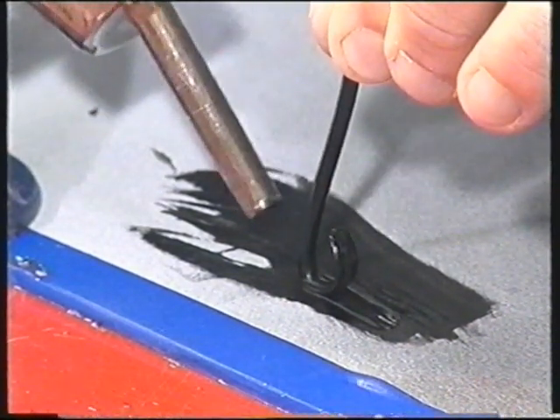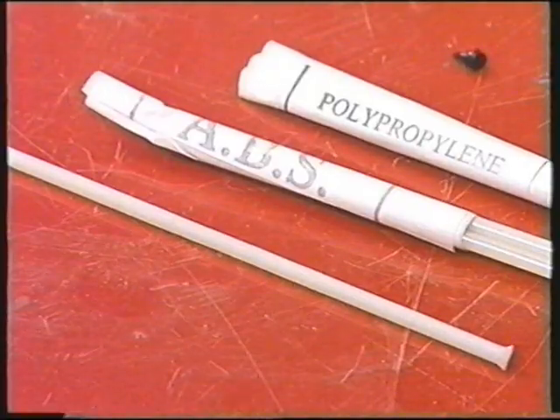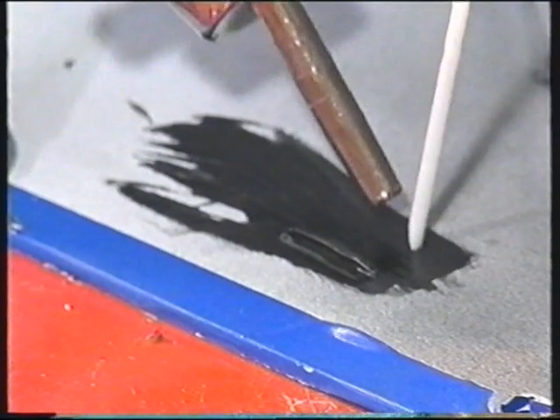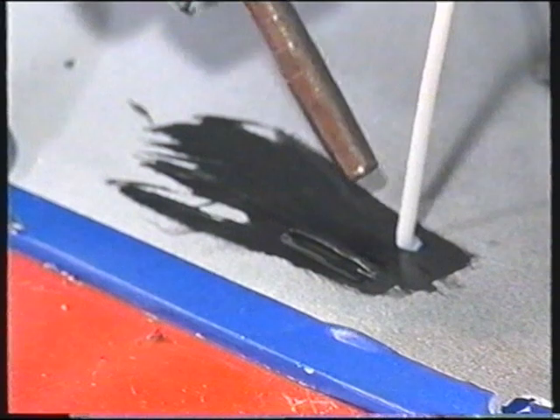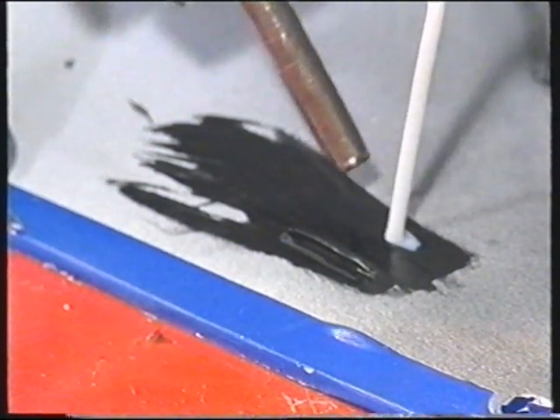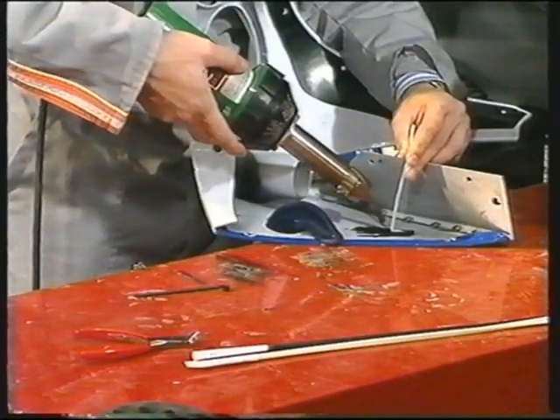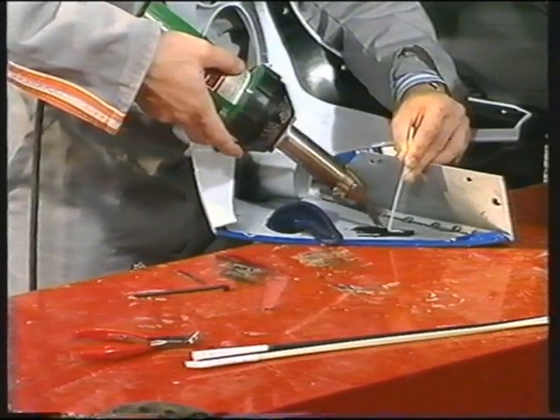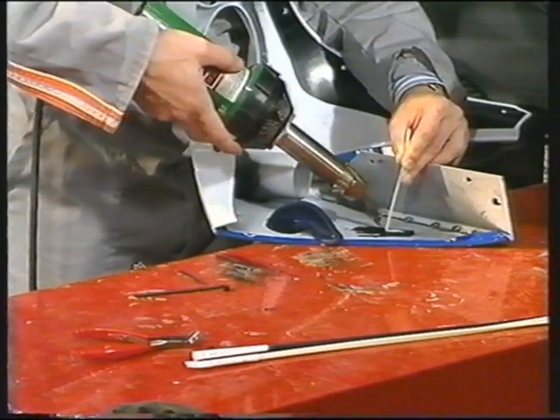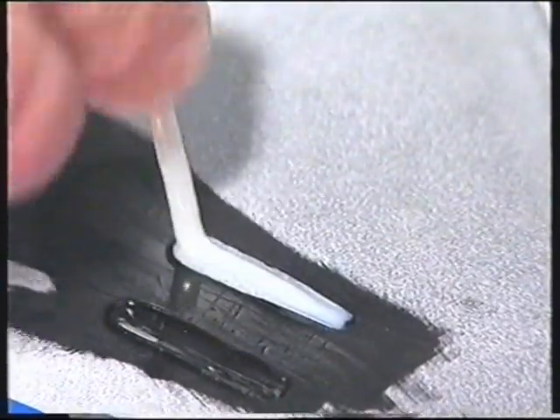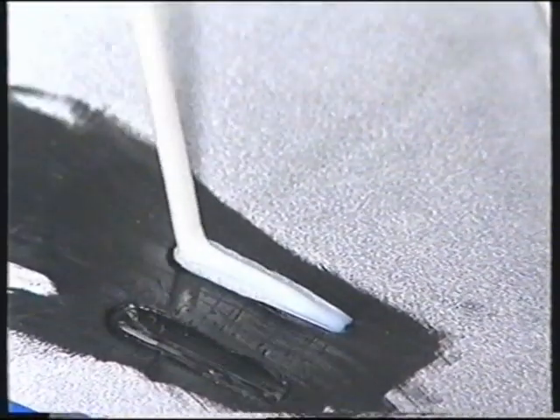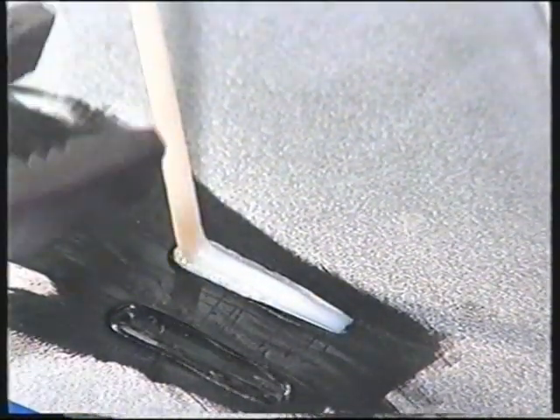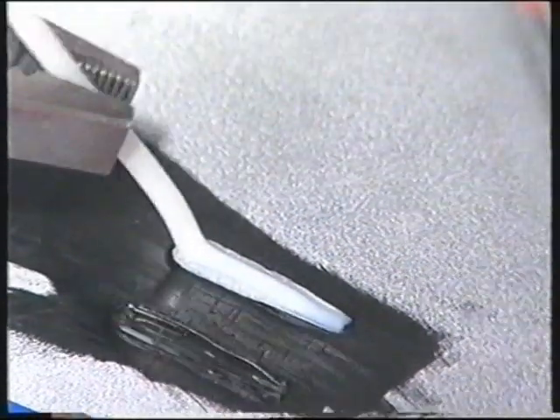The polypropylene rod will not fuse at all with the base material, whereas the ABS rod appears to bond strongly to the test area. Test welds should always be carried out on scrap material or on a well-concealed part of the panel. After cooling, only the tail pulls off the ABS rod, confirming that the component is manufactured from ABS or a compatible material.